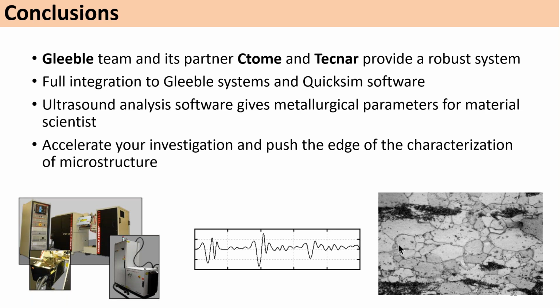So it is recommended before a test to have a sample which has no oxide scale from the hot rolling, because this tends to reduce the reflectivity of the light and therefore reduce the amplitude of the signal that we measure. So it's often a good idea to polish the sample or to have a sample machined which has no oxide scale from the hot rolling.